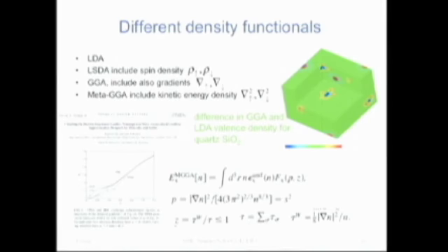We carry everything through exactly the same as I've shown it up to now, except that now we split the two terms. And now we have an exchange part of the exchange correlation potential and a correlation part of that, which both together will help you describe magnetic systems. So you can do DFT even in the lowest level approximation, local spin density approximation, and for magnetic systems. If you do BCC iron, you'll find that BCC iron is magnetic with a magnetic moment that's not that far off from experiment and so forth.